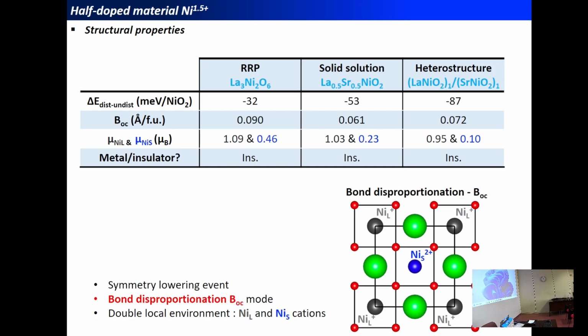And so this is observed experimentally only in this compound. So far, this type of solid solution has not been synthesized. Very likely, that's the miscibility limit of the strontium within the lanthanum nickel oxide 2 structure.